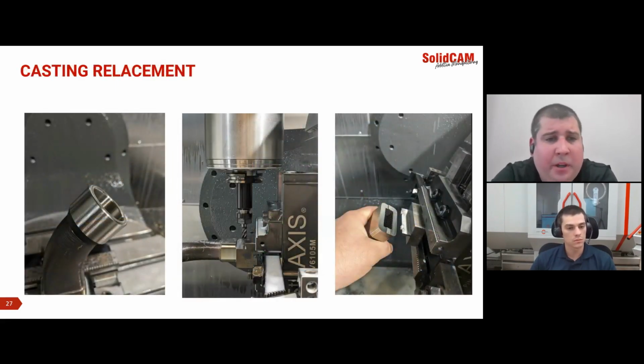Casting replacement, this was that part that we actually worked on at IMTS back in 2020. We made about 15 of these components during the show, which reduced the lead time to get this custom casting made for a customer. And we were able to really only machine the areas that we needed to. So this is essentially a funnel where we needed to machine the OD and ID of both ends, where it goes from a round flange to a rectangular flange. So we didn't have to machine the outside or inside of the curved portion of this piece, but certainly could if the requirement was there.